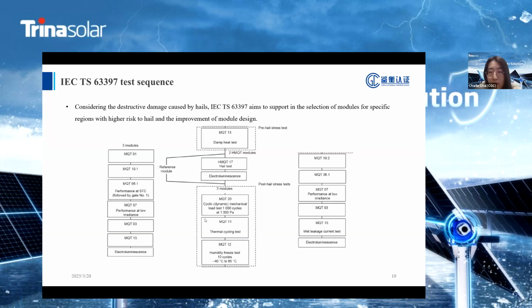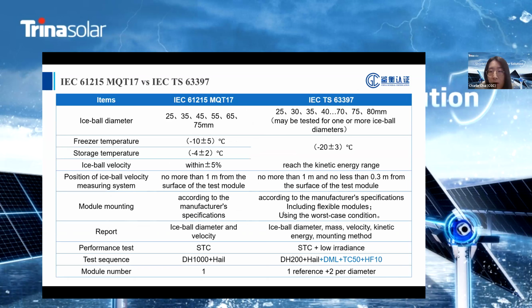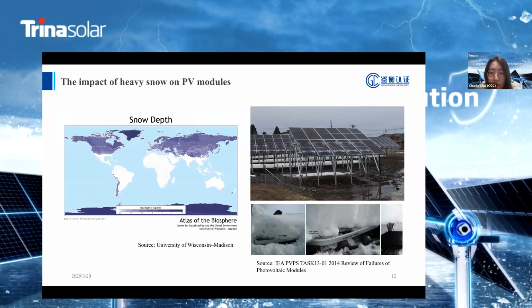Here is the test sequence. Compared to IEC 61215 MQT 17, the main difference is the sequence. In this test, after modules are exposed to hail stresses, the selected thermomechanical stress tests highlighted in blue, with dynamic mechanical load, thermal cycling, and humidity freeze, are added to amplify the influence of micro cracks caused by hail. The power loss from these modules is then compared to the reference module that has been through the same stress test except the hail stress. Okay, that's a brief description of hail.